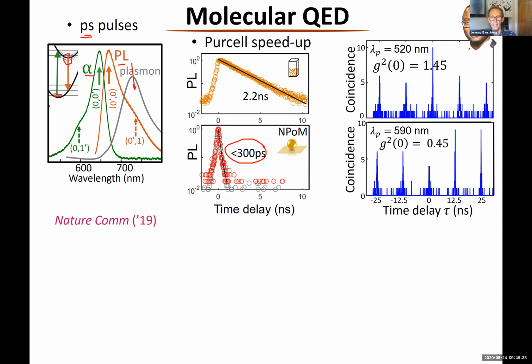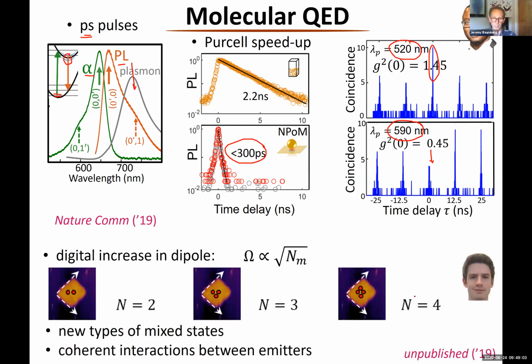So for people who've seen this sort of work before, essentially what this is showing you is the probability that only a single photon comes out of this construct. And this dip here for 0 time delay shows us that indeed this is a quantum emitter. But it actually depends on where we excite the system. If we excite at higher energy, we find it's more likely that we get 2 photons coming out. This peak here shows that in fact 2 photons come out at once. So that's probably something about the cascade, but it's still not really understood in the system.